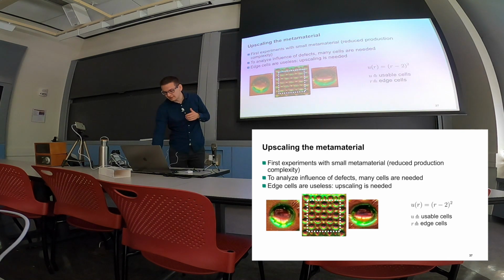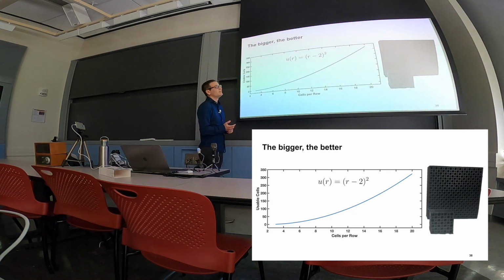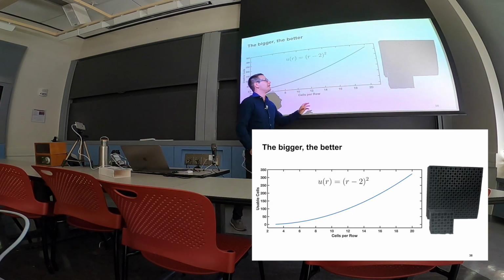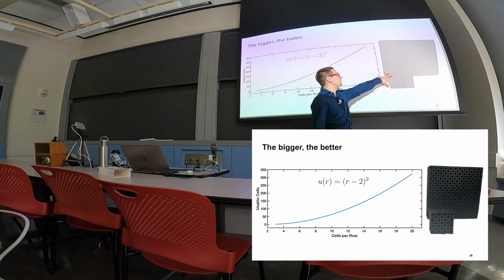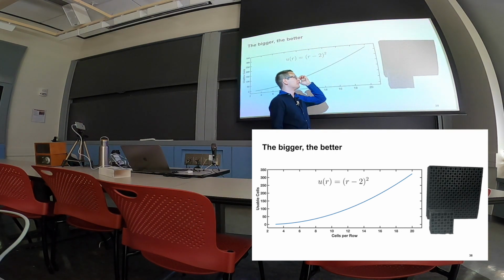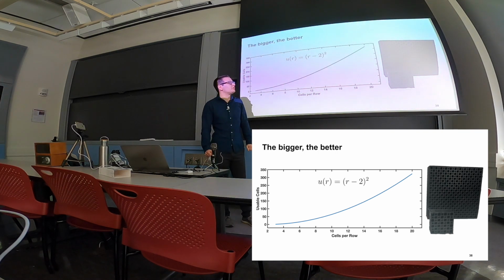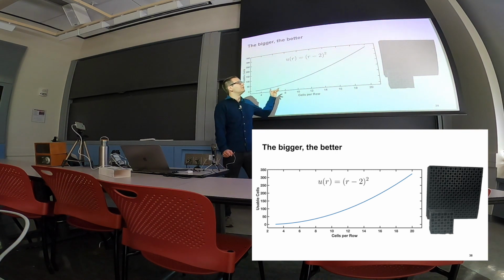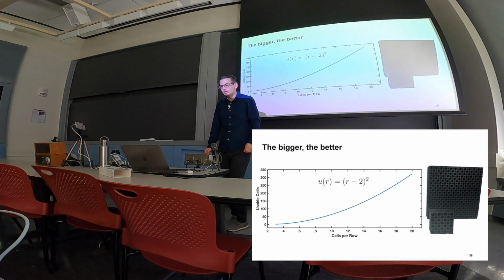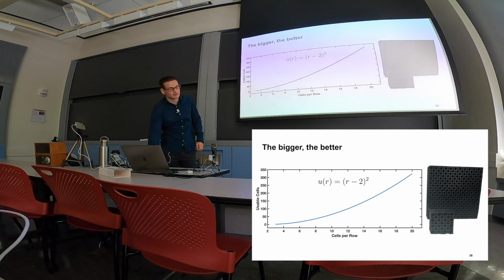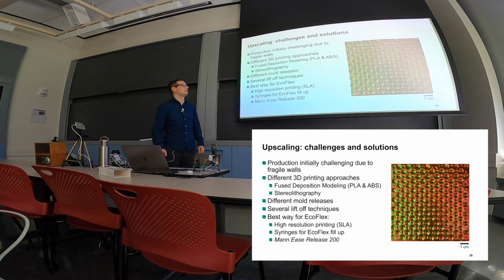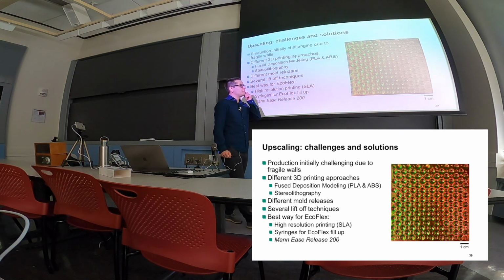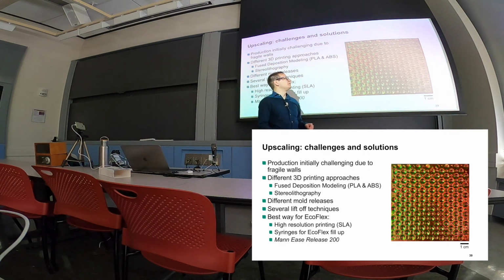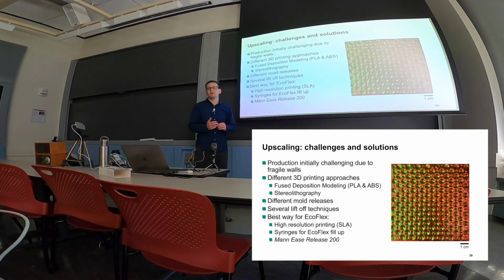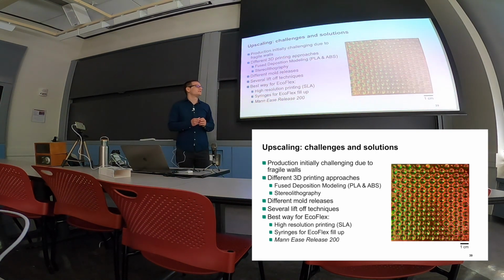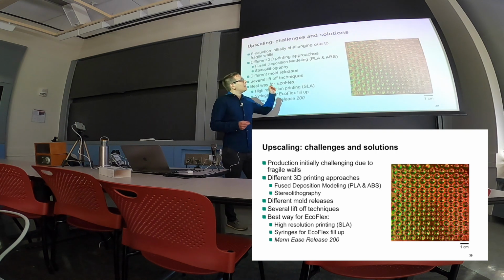And so I knew upscaling is needed, and this took me around 2 months probably to do. So I had the small metamaterial, what we see here on the bottom right side, standing in front of the big metamaterial, and this upscaling process, as mentioned, was tricky, but needed to get to know more about the influence of the overall network when applying defects or anything like that. And once I was able to do that, we can see that by applying the color changing material, nothing changed. So I could still do that even in an upscaled way. The production was the same and worked out quite well.